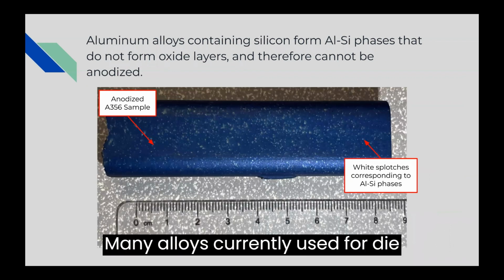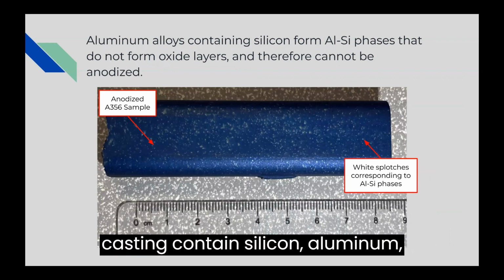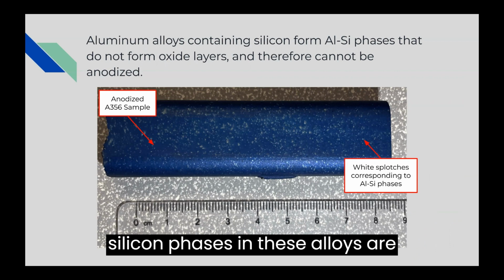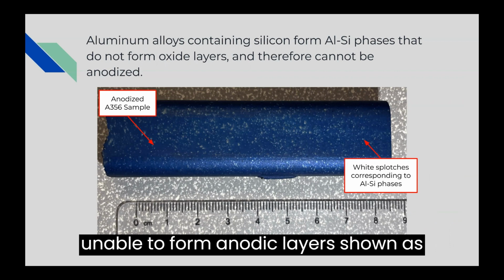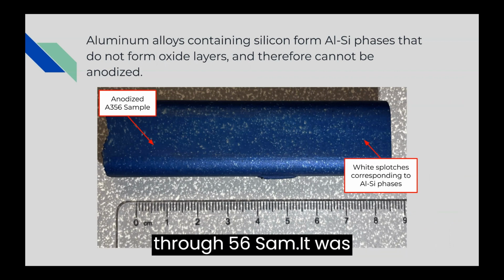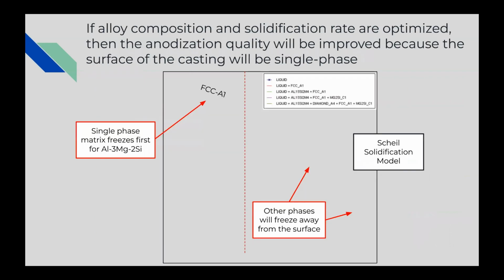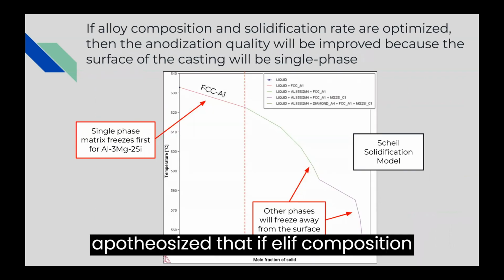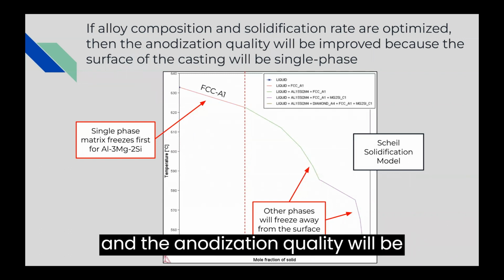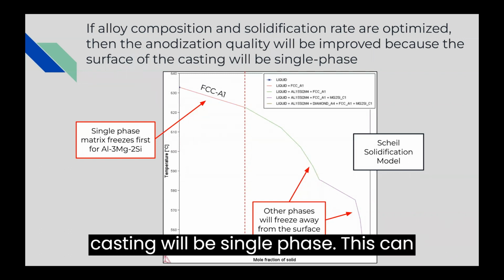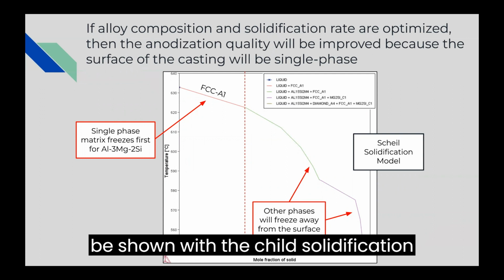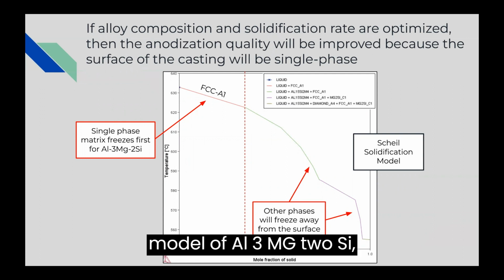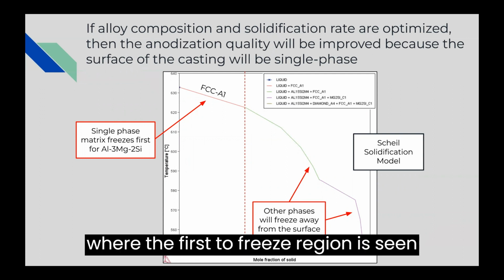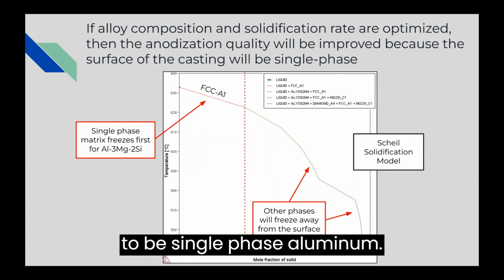Many alloys currently used for die casting contain silicon. Aluminum silicon phases in these alloys are unable to form anodic layers, shown as the white spots on this anodized A356 sample. It was hypothesized that if alloy composition and solidification rate are optimized, then the anodization quality will be improved because the surface of the casting will be single phase. This can be shown with the Scheil solidification model of Al3Mg2Si, where the first to freeze region is seen to be single phase aluminum.